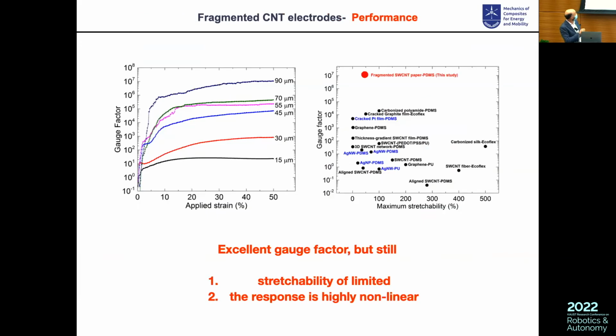But what is important is that if you look at this, you get a system with a piezoresistive gauge factor that can go up to 10^6 with a stretchability up to 20-30%. So you have a very good gauge factor, but the response is highly nonlinear, and the stretchability is limited. Here you see that you still don't get the 100% stretchability that you would like to get for your application. So that means we bring the piezoresistivity, but not the stretchability.